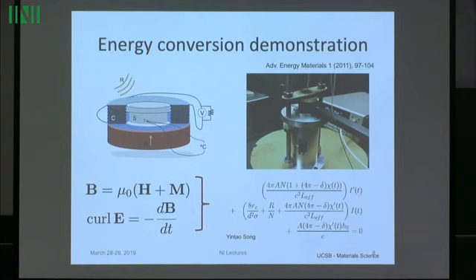That's the key term in deciding how much dm/dt goes into dH/dt and how much goes into dB/dt. And it's very shape dependent. So if I have a body, and this is again related to Peter's talk, where he was talking about ellipsoids and the fact that there was an N perpendicular and an N parallel, and these can change depending on the aspect ratio of the ellipsoid. That's what it's all about. So if you make the right kind of ellipsoid, a big dm/dt will give you a big dB/dt.